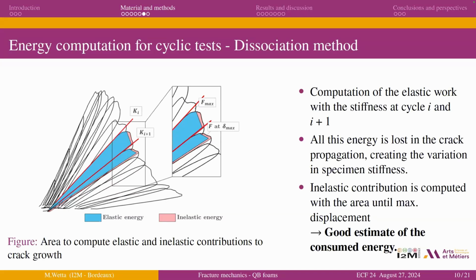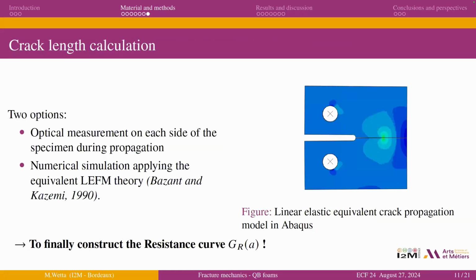So by doing that, by cycling, you have a good estimate of the consumed energy. And the last thing we need to construct the resistance curve is the crack length calculation. For that, we have two options. First one is the experimental possibility. For that, we made some optical measurements on each side of the specimen. And the other possibility is to apply the equivalent LEFM theory to estimate the linear elastic equivalent crack length by numerical simulation. And finally, if you have both these parameters, you can construct the resistance curve.